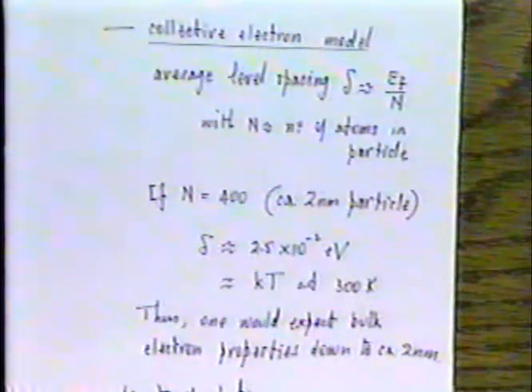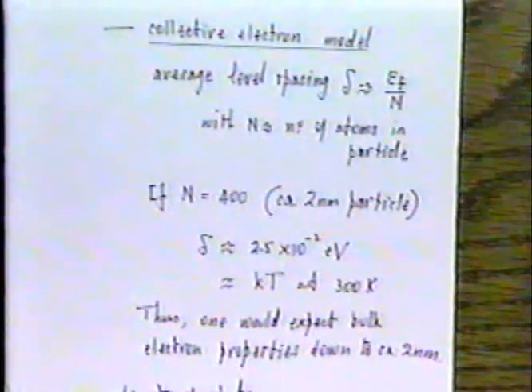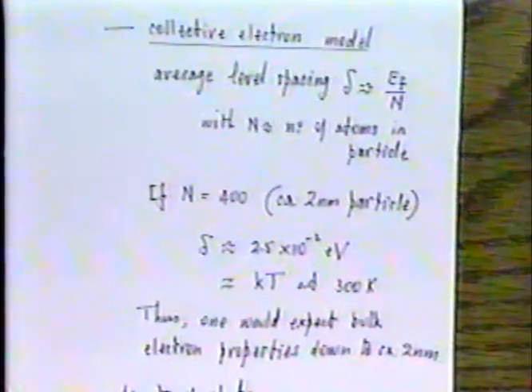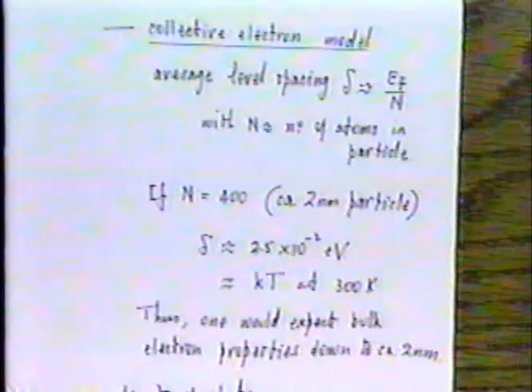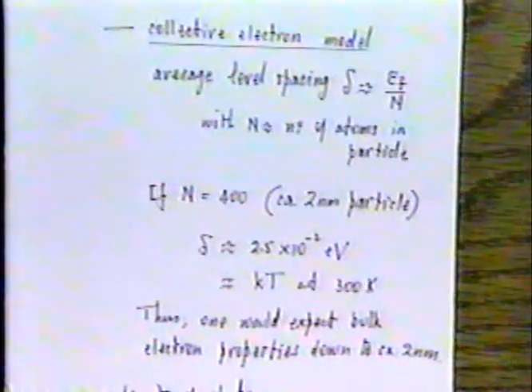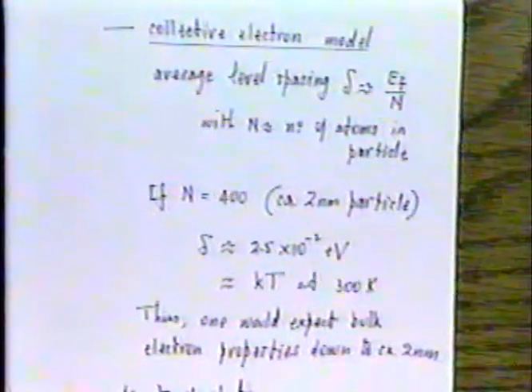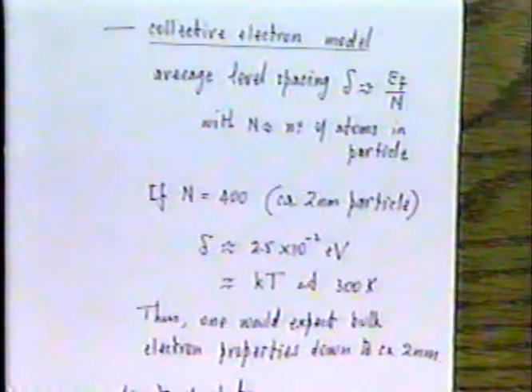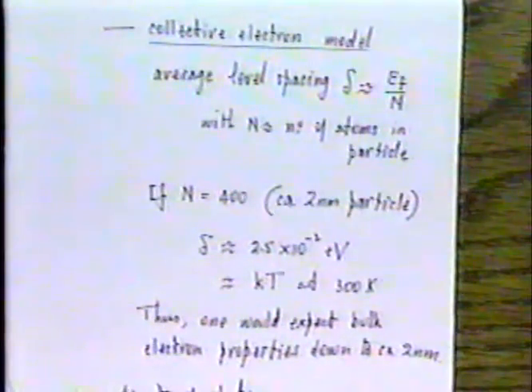And if you say, well, I'm dealing with room temperature, the thermal energy is kT, which is about 2.5 by 10 to the minus 2 eV, and you get about 2.5 by 10 to the minus 2 eV when the number of atoms in the crystal is about 400. And that corresponds roughly to a crystal that's about 20 angstroms, 2 nanometers across. So as a hand-waving sort of guess, it's not unreasonable to say that small particles that are of the order of 20 angstroms in size and smaller